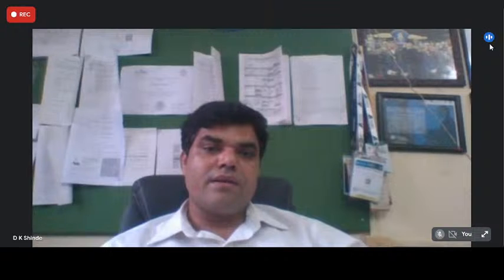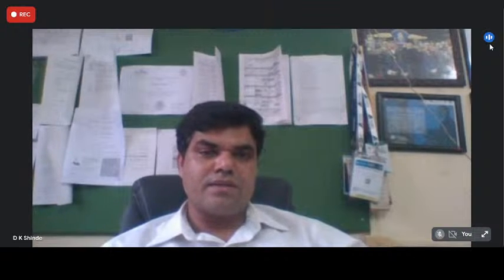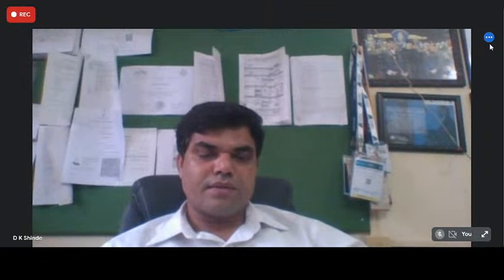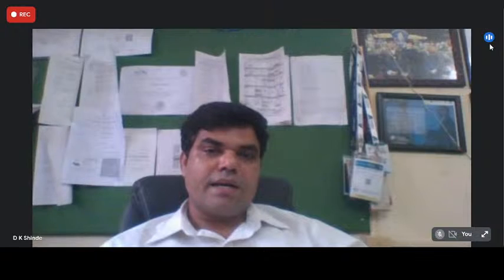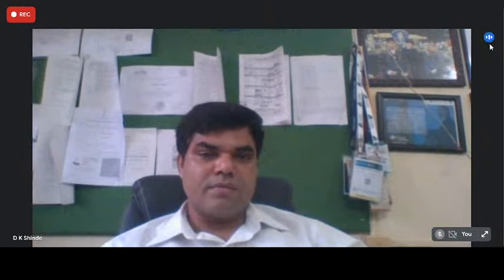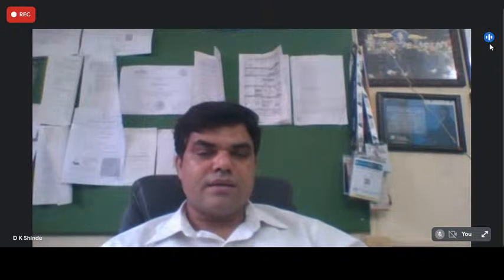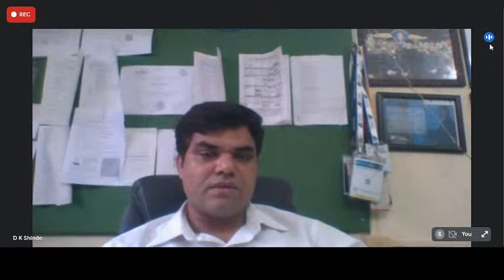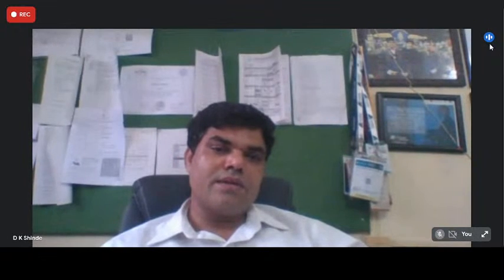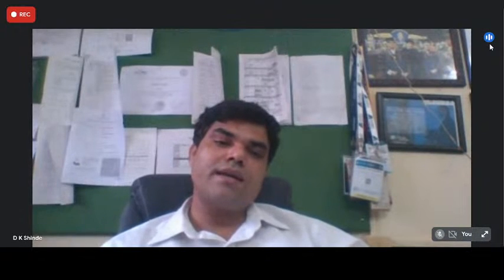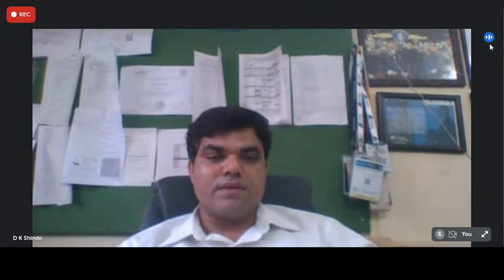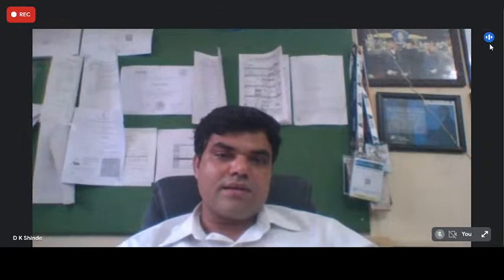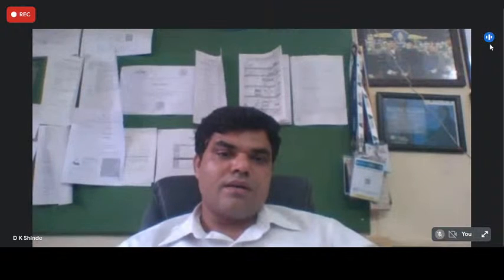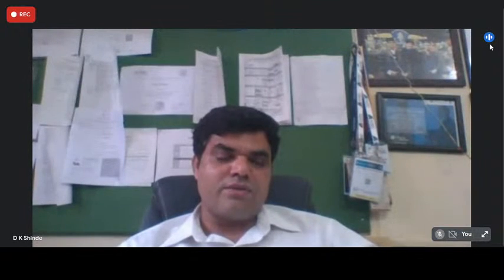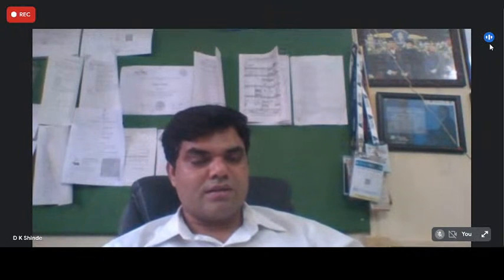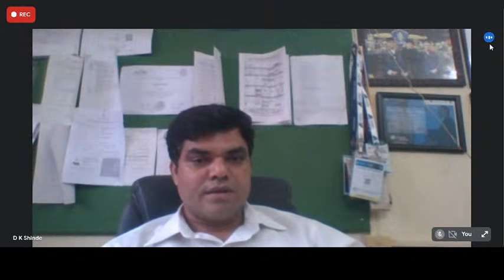Now, what we have done with the 0.1 weight percentage, we did the tensile strength for this one. By adding this, it has been improved by almost 6 megapascal higher, and their corresponding deviation to see whether the material is consistent or not. So 25 again reduced to 20, and so the tensile strength is reduced. Even though we add it, it becomes again a reduction in the tensile strength. So like that, in each of those cases, the tensile strength for 0.1 has been consistently reduced by reducing the volume percent and weight percent. Selection of the pattern also, infill pattern.